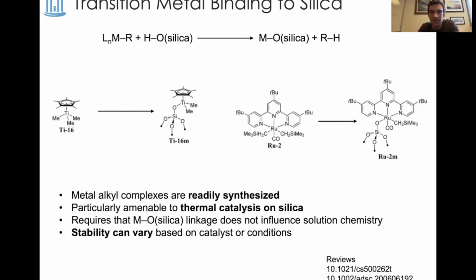So it's clearly very directly linked to the chemistry of the transition metal center. The stability varies a lot as well, depending on the strength of these metal oxygen bonds. So early metals with their stronger metal oxygen bonds tend to survive longer in these sorts of surfaces than later metals.